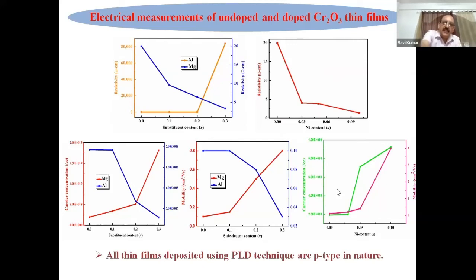Whereas in the aluminium case, it is insulating, going to 80 kilo ohm centimeter. That means aluminium is not showing conductivity, whereas magnesium is showing conductivity. Here in the case of nickel, again the conductivity is decreasing, and it's going even less than 1 ohm centimeter with nickel at 10% or so.